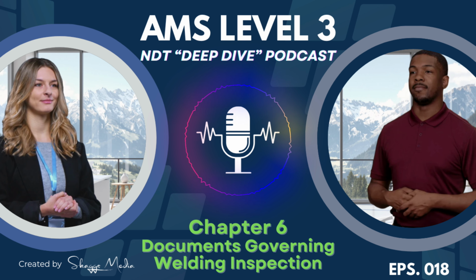Under AWS D1.1, for example, if a welder successfully passes a groove weld test on a 3/8-inch thick plate, they get what's called limited thickness qualification. Typically, this qualifies them to weld production material from 1/8-inch up to twice the test thickness, so 3/4-inch in this